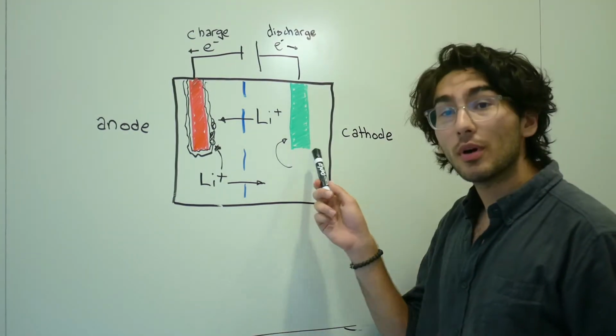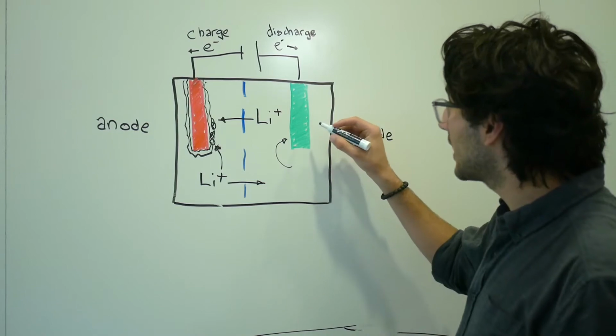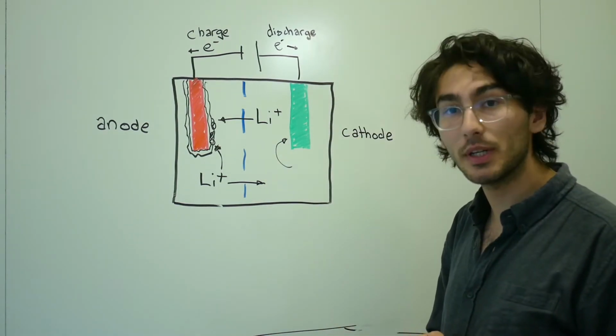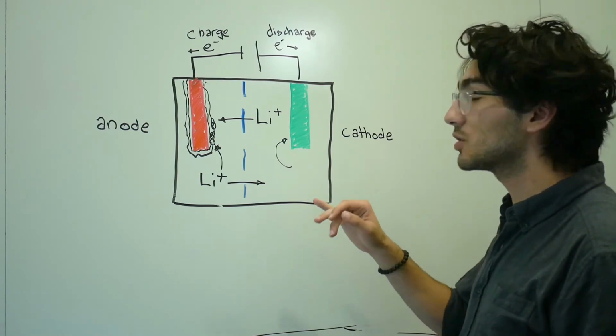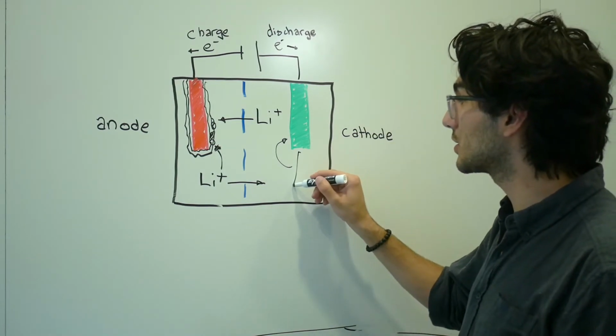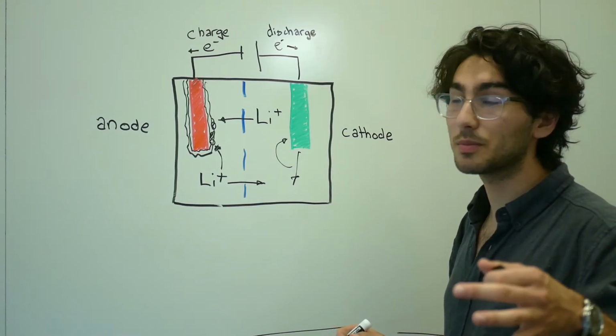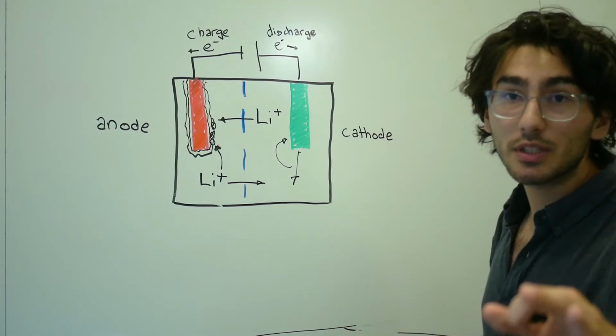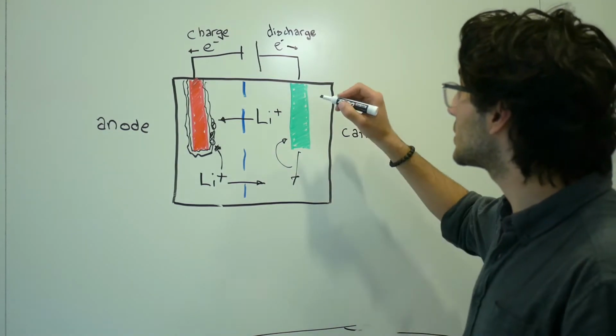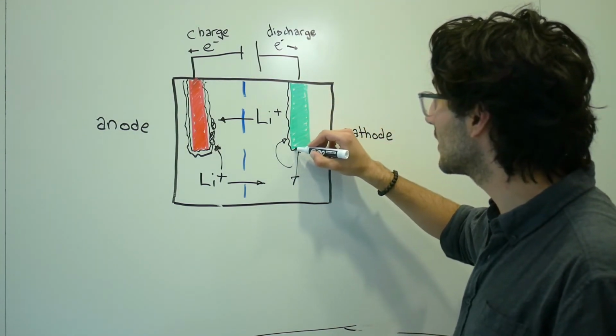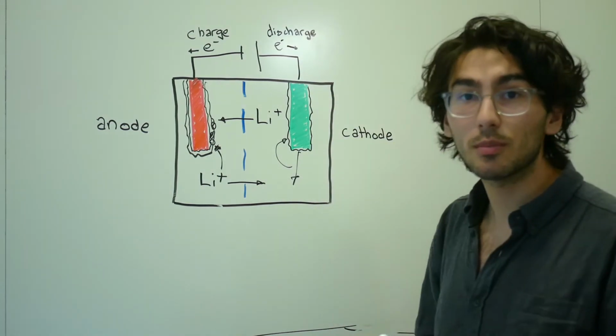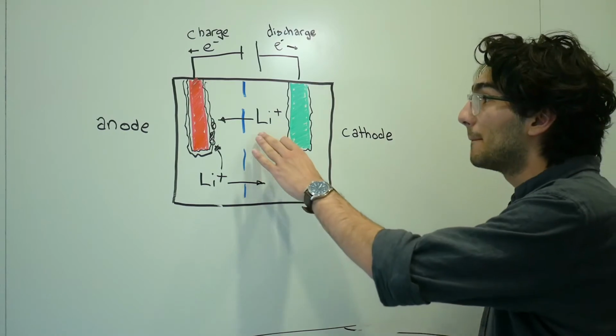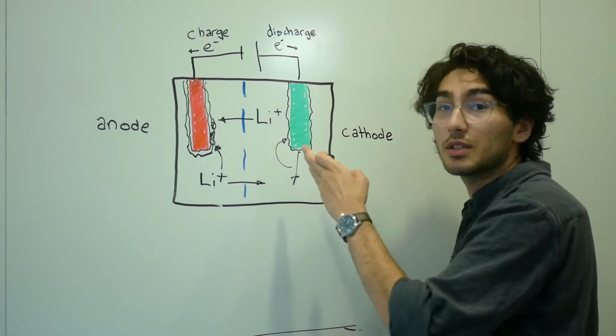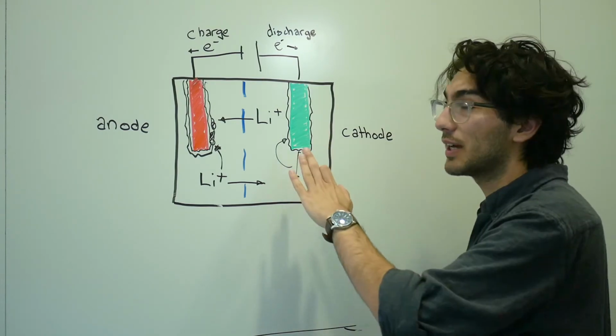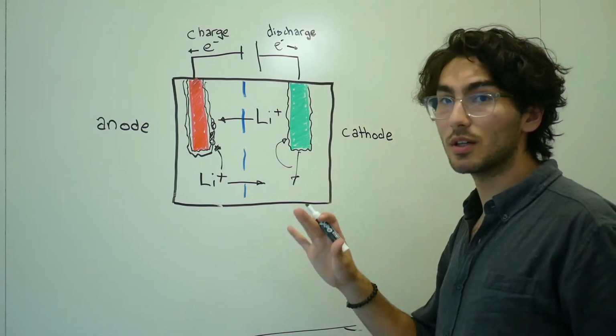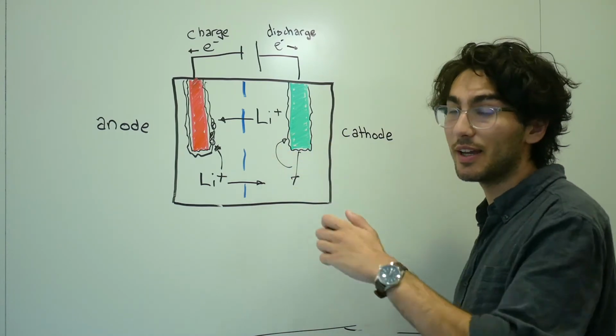Lastly, the lithium cobalt oxide of the cathode can actually lose oxygen atoms from its lattice. And what this does is it causes transition metal dissolution into the electrolyte. As we've mentioned multiple times before, this will decrease battery performance. But what this can also do is cause a rock salt formation. And this is like the SEI layer on the anode, but you're basically going to form a layer around your cathode that might catch lithium ions in it and increase the resistivity of this electrode. And all of these things together on the positive electrode can lead to a lot of decay of battery performance.